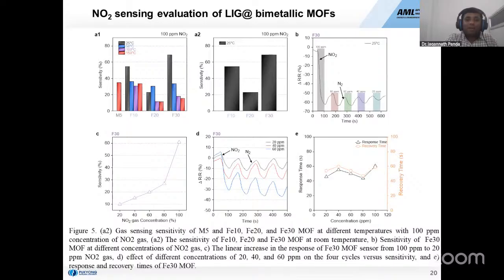Only the iron is introduced into the framework of the MOF. Then the sensing part: we performed the sensing, like NO2 sensing. We performed it at different temperatures like 150 degrees, 100 degrees, 50 degrees, and 25 degrees. Mainly, we are measuring the sensing property at room temperature because we are making flexible sensors. We got good sensitivity and also selectivity.